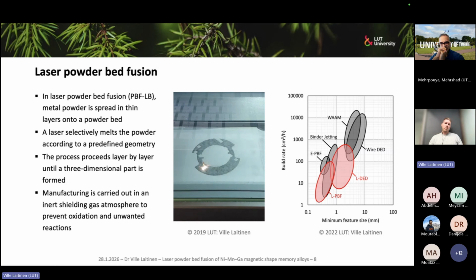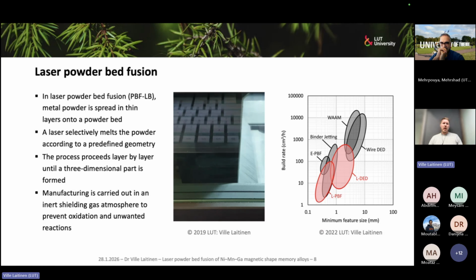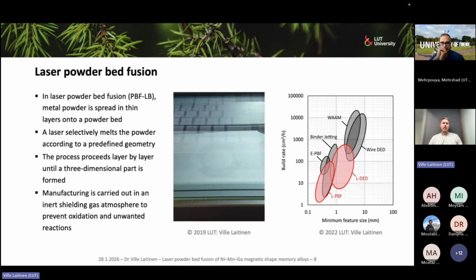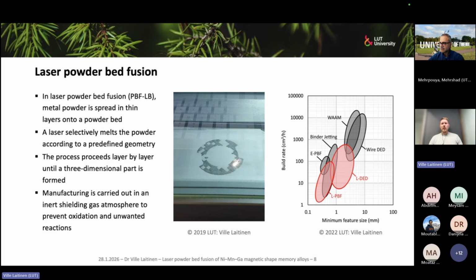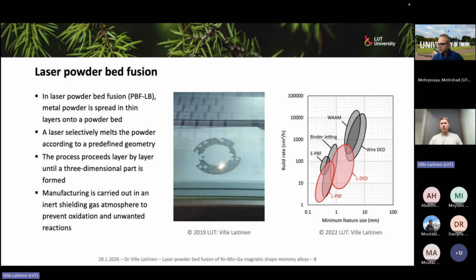The second reason we use laser powder bed fusion is the feature resolution. With laser powder bed fusion, we can actually make very, very small actuators. And this type of metallic smart material performs exceptionally well when made into very small devices. In such very small devices, conventional mechanisms, like electric motors for example, are very difficult to manufacture. So smart materials have a big competitive advantage there.